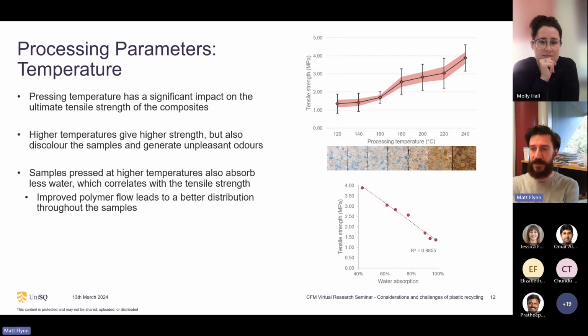So we've taken cold cups as the example because it's sort of an intermediate in plastic content of all the products out there that could go through this process. And we just had a look at the effects of some of the different processing parameters. So the temperature, you can see it in the graph here. As you get to high temperatures, you get better mechanical properties of the ultimate product, but it also starts to burn and really starts to smell quite bad.